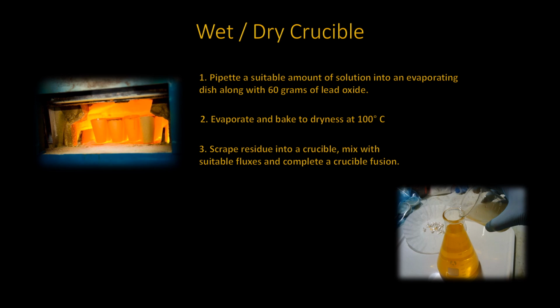On the other hand, you can add your solution to 60 grams of lead oxide, which is placed on an evaporating dish or tray. Let it evaporate and bake at 100 degrees centigrade until perfectly dry. Mix it thoroughly with the required suitable flux material and conduct a crucible fusion.